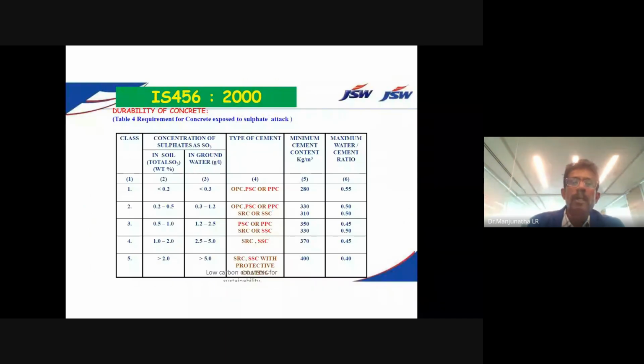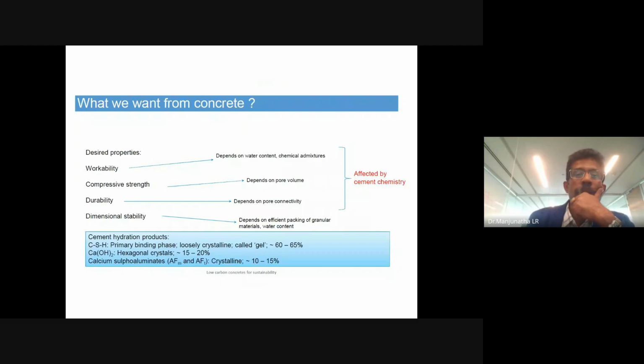Meanwhile, durability parameters are coming, sulfate and chloride resistance based on the environmental conditions. We need to really work very closely. What kind of cement and what kind of blended mix of OPC, GGBS or fly ash will be effective based on the sulfate resistance and chloride resistance.